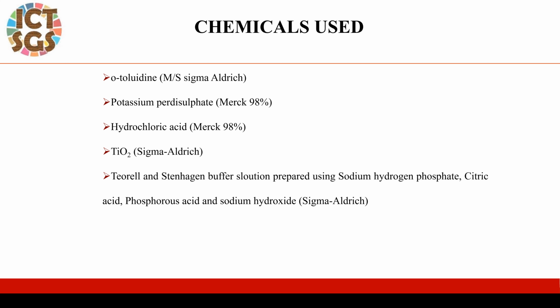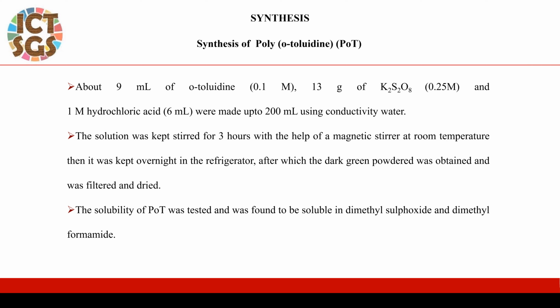These are the chemicals used to prepare polymer and polymer metal oxide nanocomposites. Synthesis. Synthesis of polymer. About 9 ml of orthotoluidine and 13 gram of potassium peroxydisulfate, 1 M hydrochloric acid were made up to 200 ml using conductivity water. The solution was kept stirred for about 3 hours with the help of a magnetic stirrer at room temperature. Then it was kept overnight in the refrigerator, after which the dark green powder was obtained and was filtered and dried. The solubility of PoT was tested and was found to be soluble in dimethyl sulfoxide and dimethyl formamide.